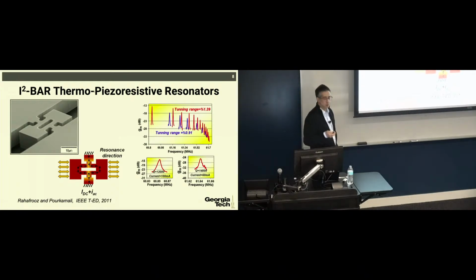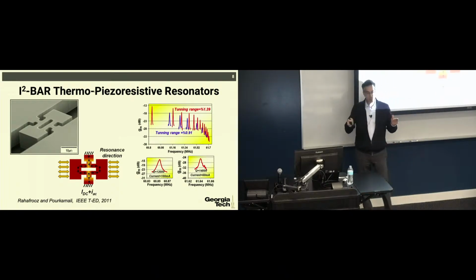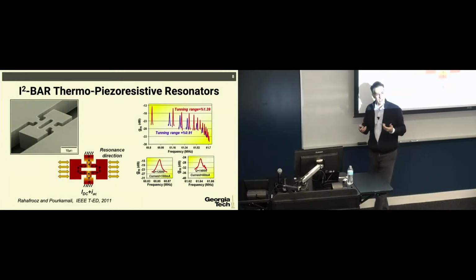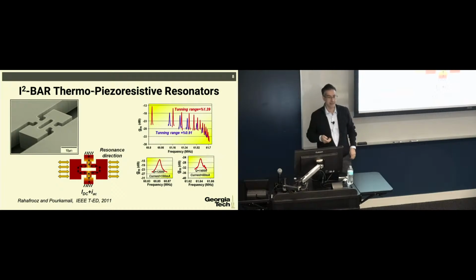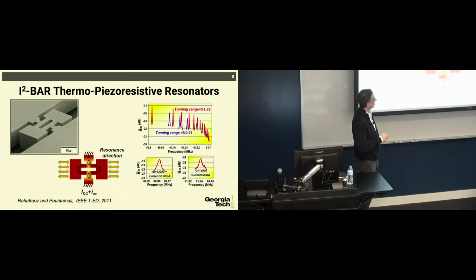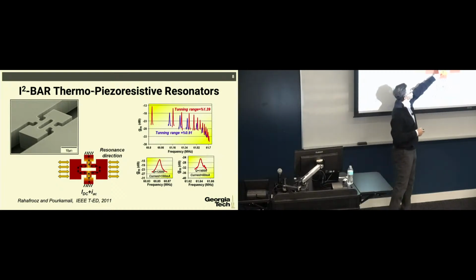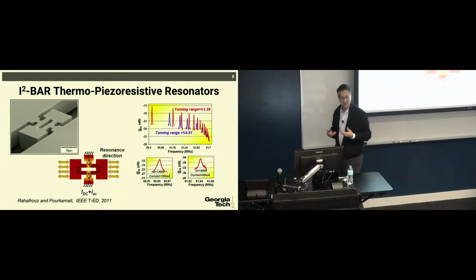And it's thermally actuated and piezo-resistively sensed, okay? And it doesn't require any external transducer or any additional transducer element. So you simply pass a current from this side to the other side. You have to have a DC current, and then on top of it, you add an AC current that coincides with the resonance frequency of this device. So this AC current would cause cooling and heating of the resonator. And if that frequency coincides with the elastic resonance of the device, you start actuating that resonance mode. And when the resonance occurs, now because of a stress at the base, you will actually get a change in the resistance of the silicon.